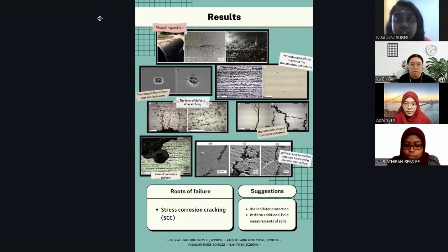In the aspect of visual inspection, figure 1A depicts pipe pieces with partial coating disbondment in the areas of the highlighted flaws, while the SCC defects on the metal surface of the pipes in figure 1B were narrow, short colonies, accumulations of cracks in the longitudinal orientation relative to the pipe axis. There were almost no corrosion flaws on the pipe surfaces around the crack sites. In the process of visual examination, corrosion pitting with a depth of up to 5 mm was discovered in other areas of the pipeline, as illustrated in figure 1C.